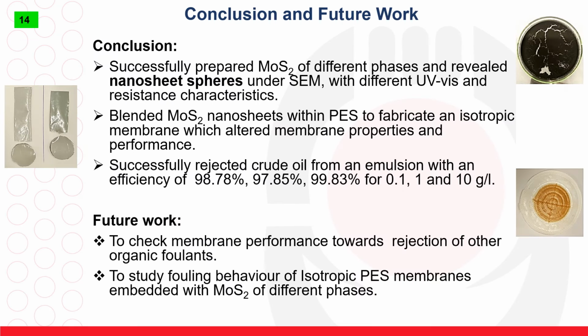which had a very good oil rejection. And therefore, we successfully prepared molybdenum disulfide nanosheets, which revealed a flower-like structure under scanning electron microscope, and were distinguished by UV spectrophotometer, as well as having different resistance characteristics. We blended the nanosheets into polyether sulfone and fabricated resultant isotropic membranes, which had different performance characteristics. The optimal membrane had a high rejection performance towards oil for an oil in water emulsion.